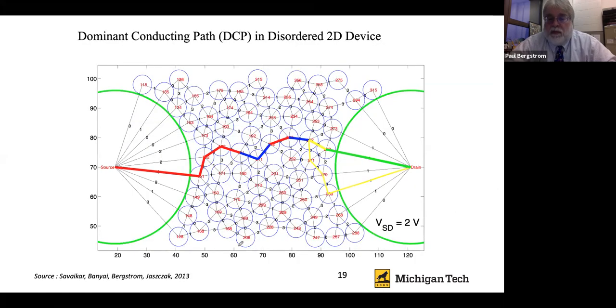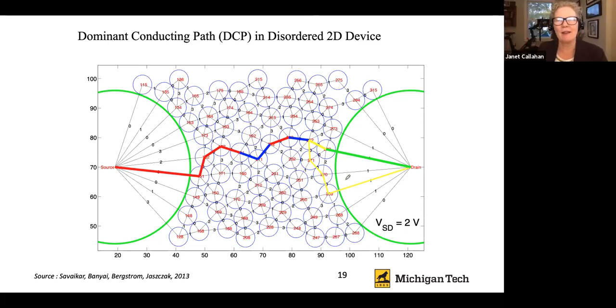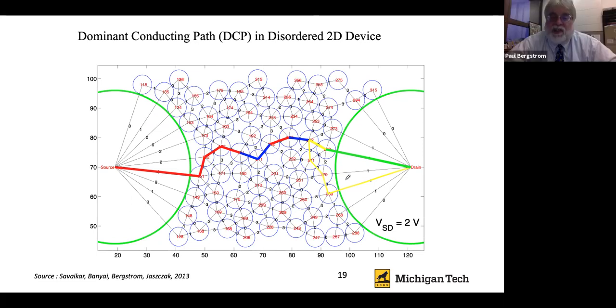And so that study gave us a very clear indication that in all these devices, there tends to be a dominant conducting path, even when you have a large array of quantum dots in between. You tend to have a path that is the most likely path for the electron transport to occur in. And so if you have a most likely path, I can see hundreds and hundreds of graduate student hours going into this model. Oh, this is a stunning amount of work. There's no question. This is a huge effort on the part primarily of actually three PhD students.